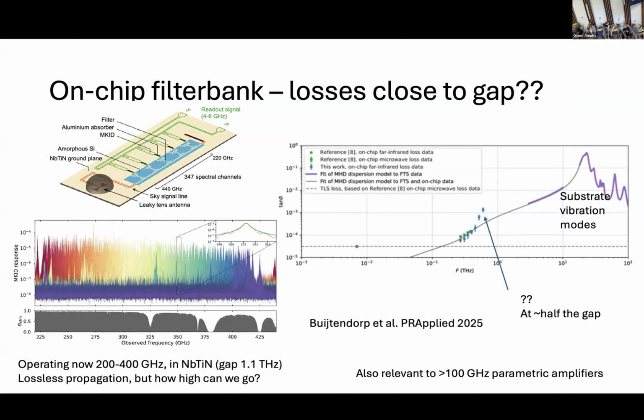But we see that closer at higher frequencies, we really start to move away from this behavior. And it also is unlikely to be TLS, if it is TLS in the conventional picture, because we have, of course, microwave measurements of our TLS loss. And if you extrapolate that with some probably crude assumptions that fit in the conventional TLS model, the TLS shouldn't be dominating in this regime. So I think this is also an interesting way to actually measure things.